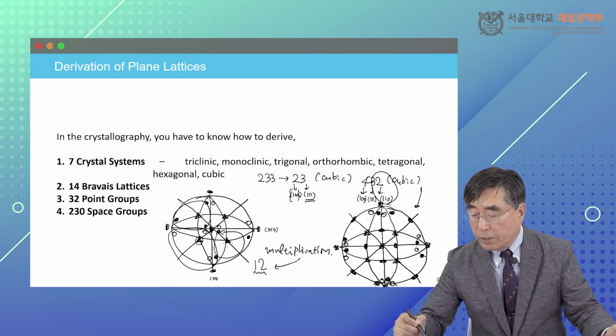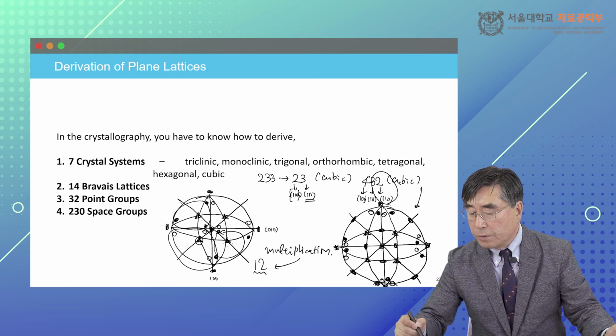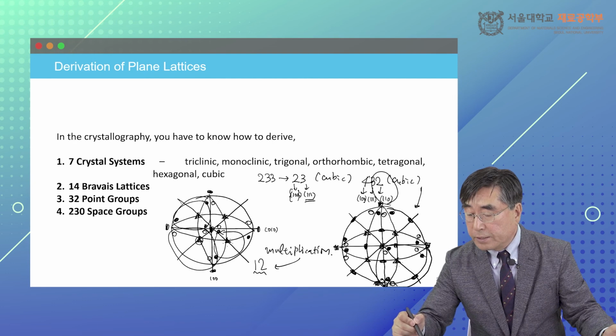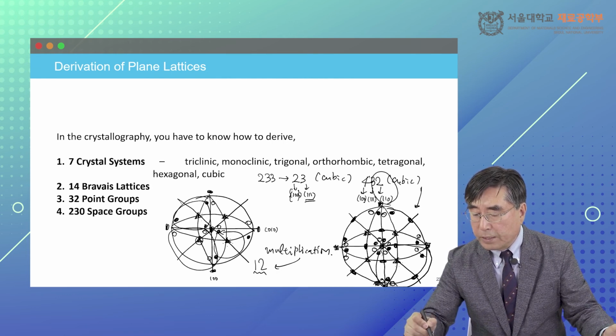Now, what I'll do is this threefold rotation operation. So in here, you should make one upper pole and down pole, so this one makes threefold rotation operations. Again, the same thing. There is an upper pole and down pole, another upper pole and down pole, and another upper pole and down pole in here by these threefold symmetry operations.